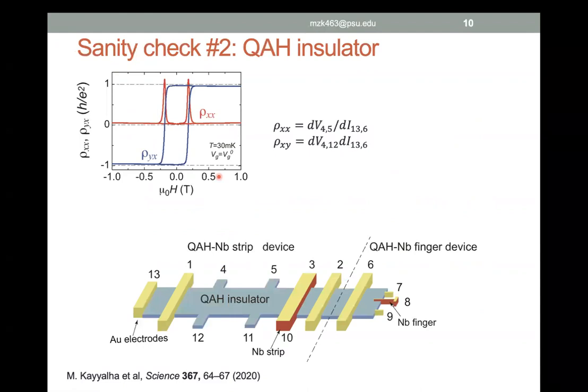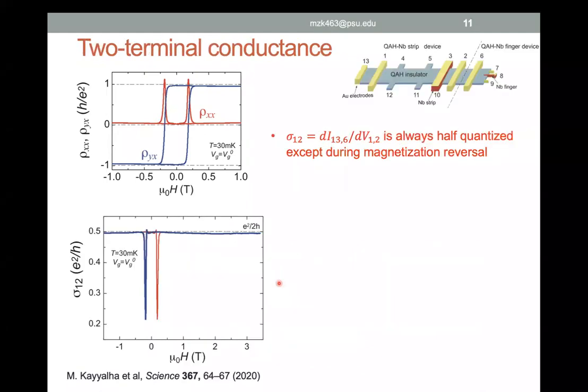Then the next sanity check was, okay, do I have quantum anomalous Hall insulator here? So I looked at the Hall bar that I had, and I see a quantized Hall resistance and vanishing longitudinal resistance when I measure the Hall bar. Then I looked into the two terminal conductance across the niobium strip. And what I see here again is that this two terminal conductance is always half quantized. The only time that it is not half quantized is during the magnetization reversal.